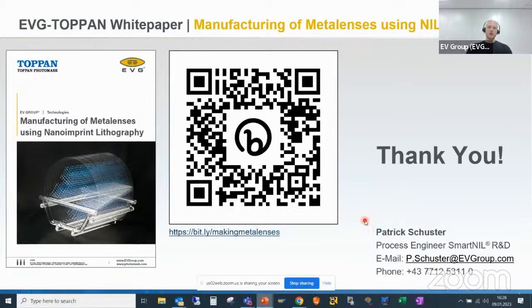Minimum features, so we can go below 50 nanometers, definitely. Then it's depending again if it's pillar structures or grating structures. But let's say 30 to 50 nanometers should be feasible. And the speed of manufacturing is also depending, because when we attach the working stamp, the capillary forces are filling the structures from the working stamps, so we do not apply an active force. Depending on the structures, this takes some time, but you can estimate the imprinting process between a few seconds to a few minutes, but for bigger structures, for example, it takes longer.